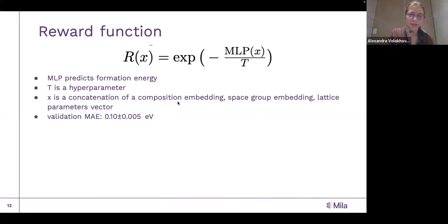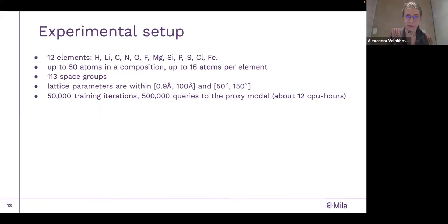Just from this model, we see that there is a lot of information within this representation of composition, space group, and lattice parameters, which allows this model to predict the energy of the crystal quite well. It's a good insight, which tells us that even without atom positions, it is possible to get some understanding of how stable the crystal can be. So this is our reward function.